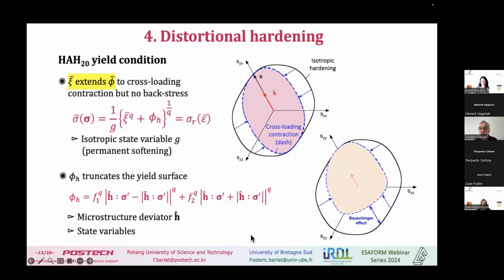And actually, if I want to do some change, so I'm going to change. Okay, I was loading in this direction here. Now I'm loading at it's cross-loading here, pure cross-loading, because it's 90 degrees in a pi plane. So the yield surface is going to rotate, and the microstructure deviator is going to rotate as well, because the microstructure deviator tends to align itself with loading, but it cannot do so instantly. Okay, it takes time to change a microstructure. So even if the loading is changed instantly, the microstructure will change, but gradually, and that's what this rotation tends to represent.